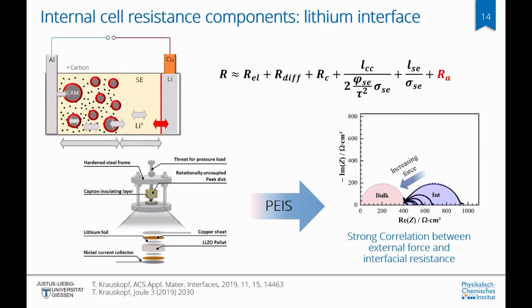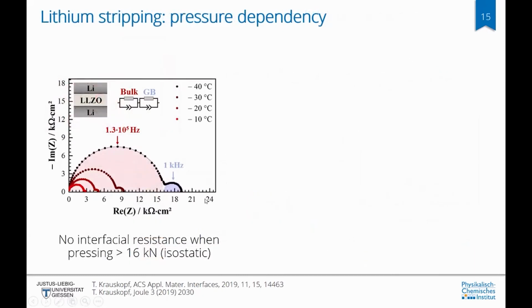But I will focus here on the interface resistance, which Torben Krauskopf has demonstrated in this cell setup, where he has a garnet pellet and 2 lithium electrodes, and then built this stack into this clamp here, where he was able to create specific forces on the cell stack and measure impedance at the same time. The result is shown here on the right, where with increasing force on the cell stack, the interface resistance, shown in blue, decreases continually, and it was even possible to remove this interface resistance completely when going to isostatic pressing and very high forces, which then forms a really close and well-contacted lithium interface.